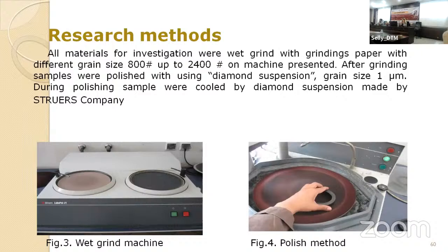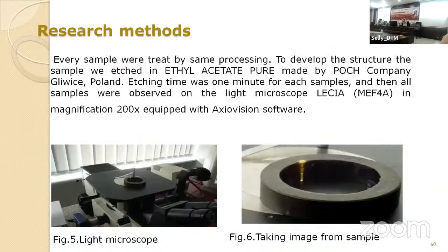All materials for investigation were ground wet with grinding paper of different sizes on the machine presented. After grinding, we polished the samples using a diamond suspension with a grain size of 1 micrometer. During polishing, the samples were cooled by the diamond suspension.